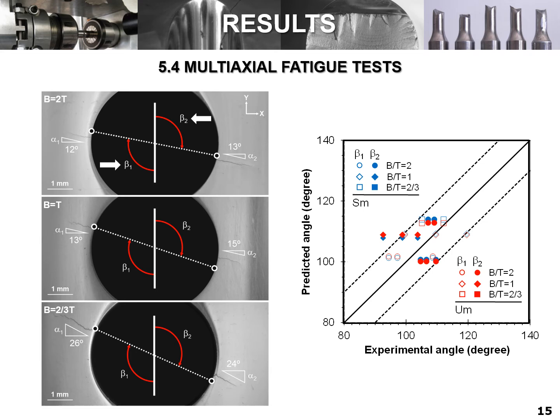Fatigue crack initiation sites can be reasonably predicted from the nodes with maximum values of the first principal stress at the whole contour. As shown in the figure, there is a very good correlation between the experimental observations and the predicted locations. In most cases, the errors are lower than 10 degrees. Moreover, the quality of predictions is not much affected by the type of finite element mesh used in the calculations. No significant differences are observed.